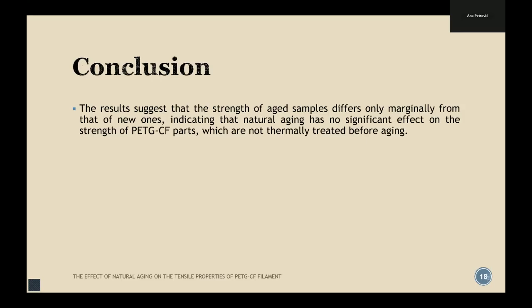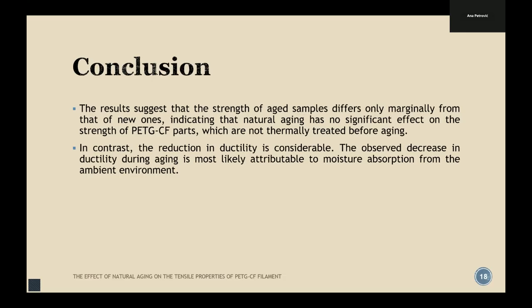So we can conclude that the results suggest that the strength of aged samples differs only marginally from the new ones, indicating that natural aging has no significant effect on the strength of PETG carbon fiber reinforced parts which are not thermally treated before aging. In contrast, the reduction in ductility is considerable. The observed decrease in ductility during aging is most likely attributed to moisture absorption from the ambient environment, so we can see an increase in brittleness.